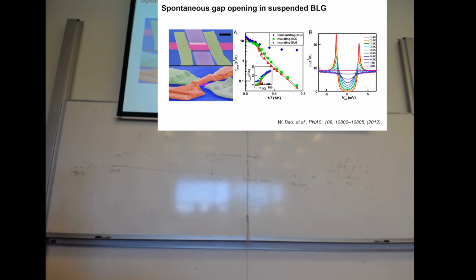At least people found that at very low temperatures, for example, a few Kelvin, the conductivity of graphene can be really killed, and there is a real insulating phase there. But the temperature is really low, it's a few Kelvins, and nobody can make this happen at room temperature. So it might be interesting for fundamental physics, but so far, for application-wise, it's still far away from what people want to obtain from graphene. So that's why, after all these years of development of theories and experiments, people can still not find any kind of products of graphene in electronics, sadly, so far.